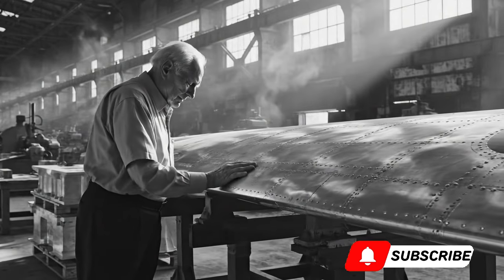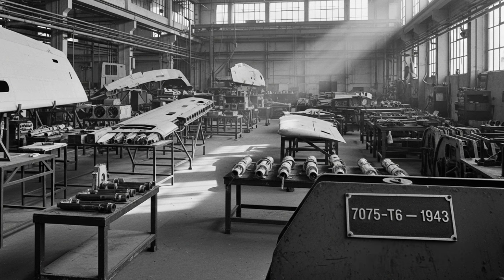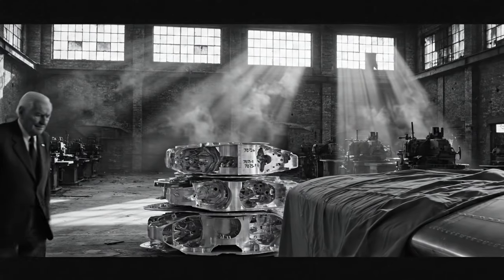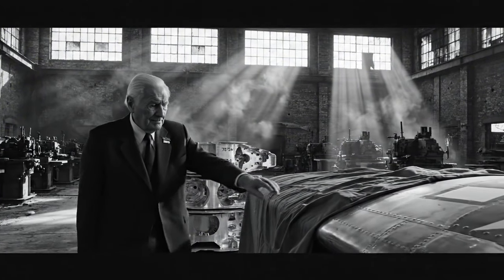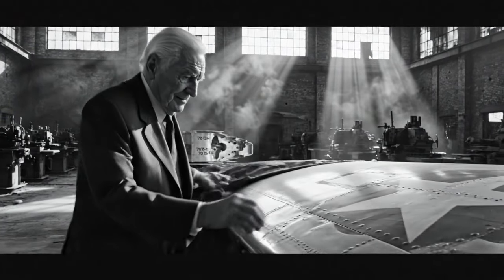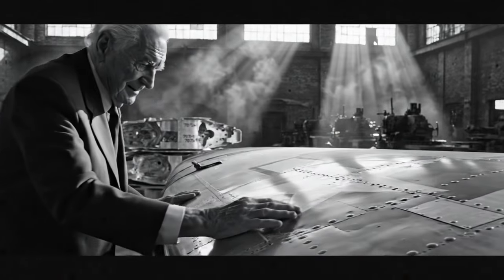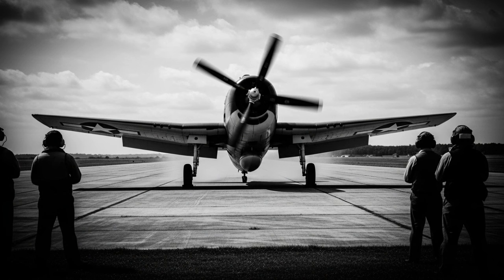It was subjected to static testing at 120% of the maximum design load. The wing sustained the load. At 150% of design load, the wing remained intact. At 180% of design load, the wing failed, but not through the propagating crack failure typical of 24S. Instead, it showed plastic deformation. The material bent rather than fractured. That's the signature of sufficient strength. The material reaches its limit by physical distortion rather than sudden, brittle failure.